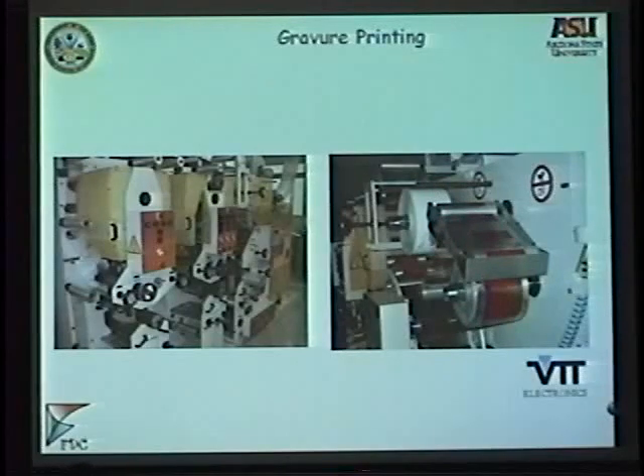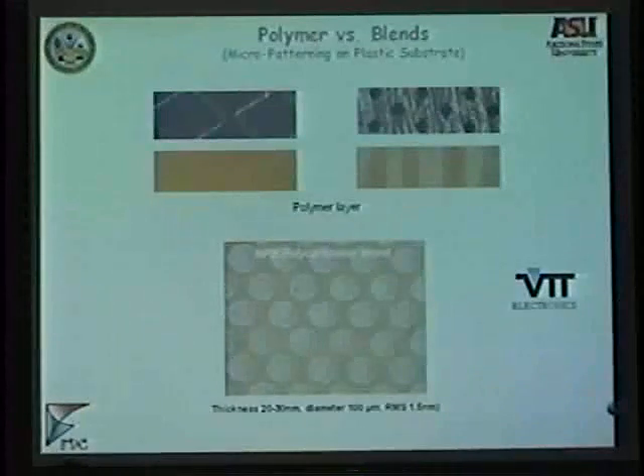I'll show you just what we did in this with VTT Electronics. We were able to print, as you could see here, 100 micron dots over a roll of film, with root mean square roughness of 1.5 nanometers, and the thickness is 20 to 30 nanometers. This is unheard of with a high-speed printer, and they are very, very nice and uniform. These edges can be taken care of by adjusting the viscosity. You can print complete layers by adjusting the size and the ink viscosity. You can print lines of polymers, and you can print dots of polymers.